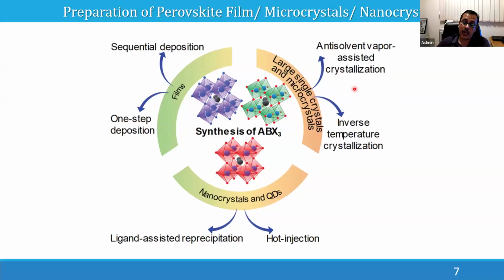You dissolve all the reagents in one solvent, and you add another solvent in the vicinity. The vapor of this solvent should be an anti-solvent. That means the material should not dissolve in that solvent. So it is an anti-solvent. This anti-solvent vapor will go inside the mixture, and that will force the material to crystallize. That is one method. Another one is the inverse temperature crystallization.